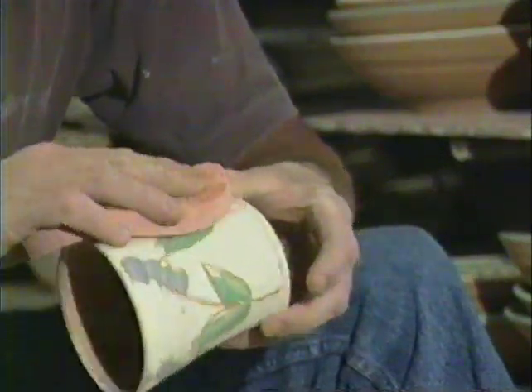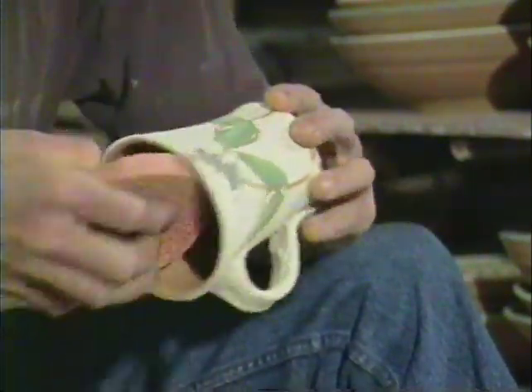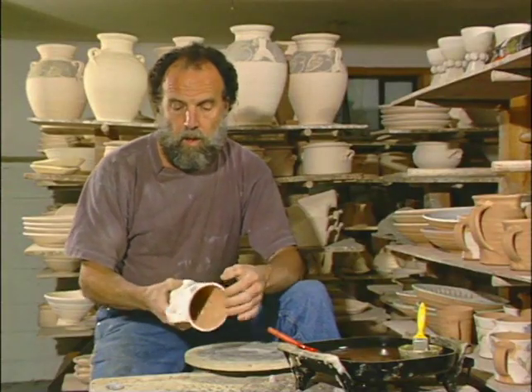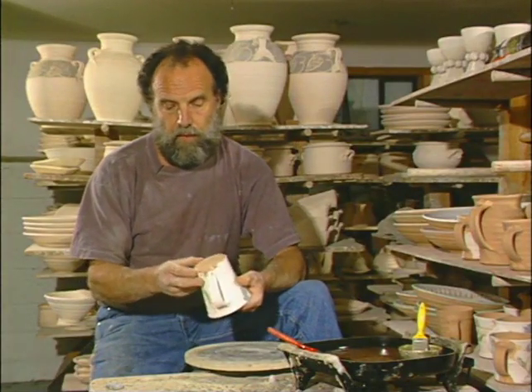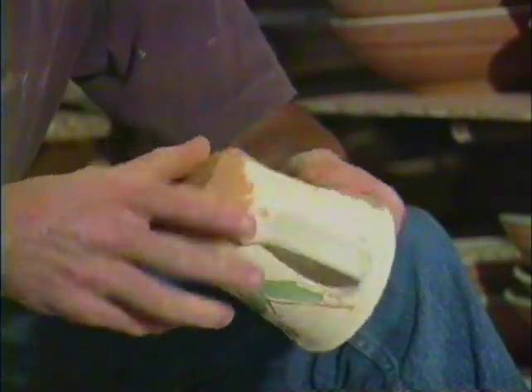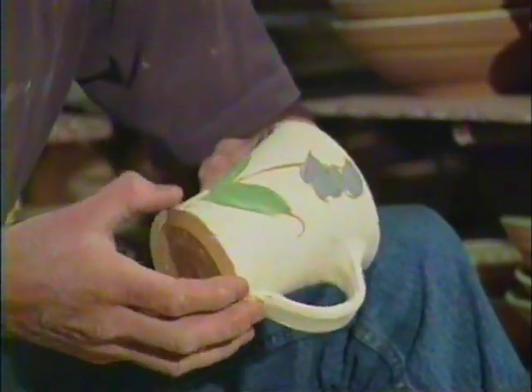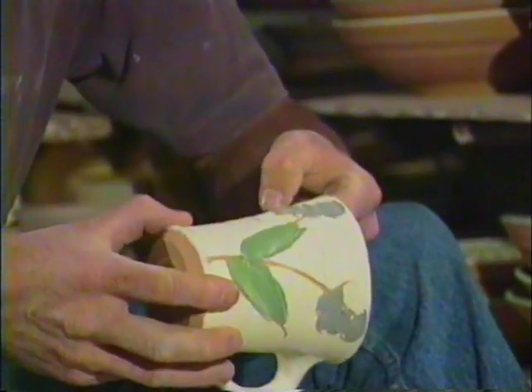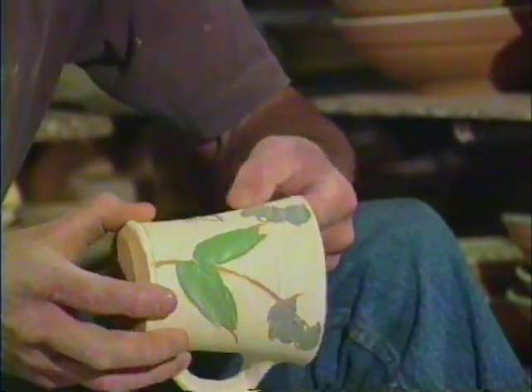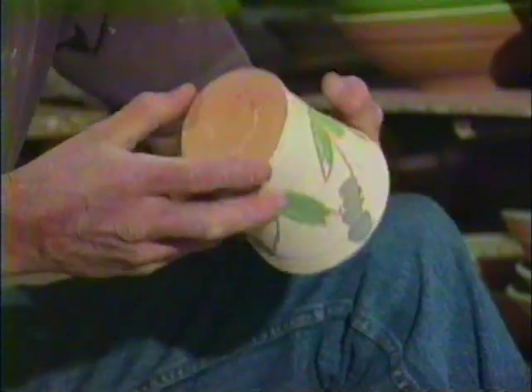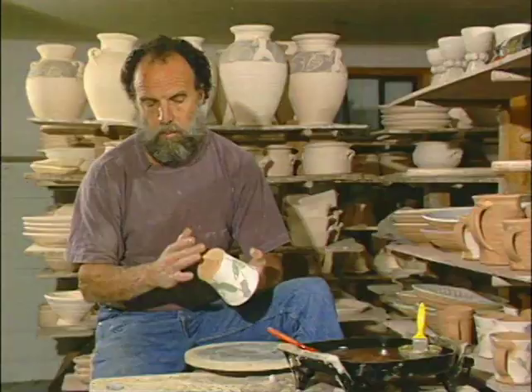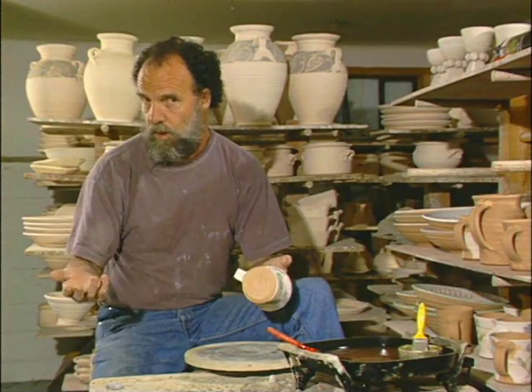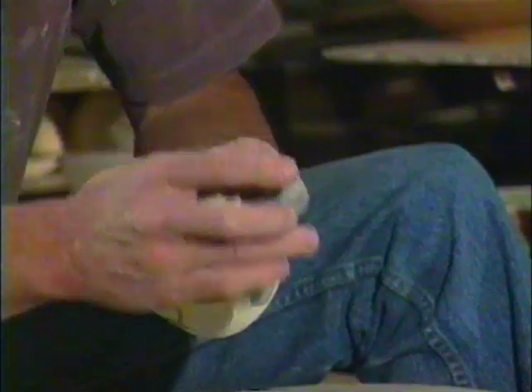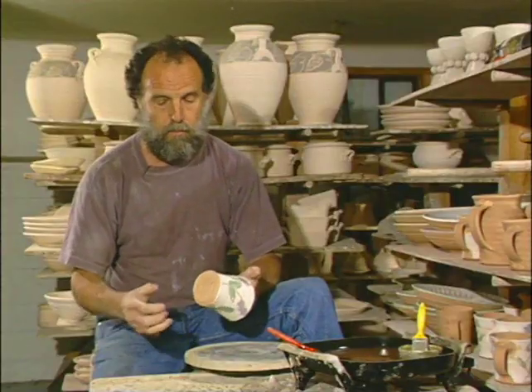Use a damp sponge, and you can sponge off any dustiness that's on the pot. This is also an opportunity to check around that there aren't any little burrs from the kiln or little pieces that you've left here, say where you've scribed through the slip, and if there are, you can flick them off with your finger. They're only bisque, so they're not too strong. Or if there's any burry little bits on the bottom, now's your opportunity to sand them off with a coarse sandpaper, or in fact, my favourite implement is a little piece of old kiln shelf, and I just make sure that the bottom's smooth before I start.